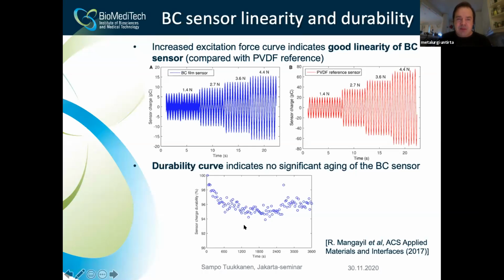And then we also measured the durability. So basically how long the sensor can work. We measured it here for about 3,600 seconds. We just keep pushing the sample for a long time and measure the output, and it seems that it remains its functionality for a long time. In the beginning there's some instability, and then when it goes to a certain level, it remains on that. So at least we see that the sensor doesn't die or get broken fast, so we can measure for a long time, which is one requirement for the sensors, so that they work for a certain time at least.